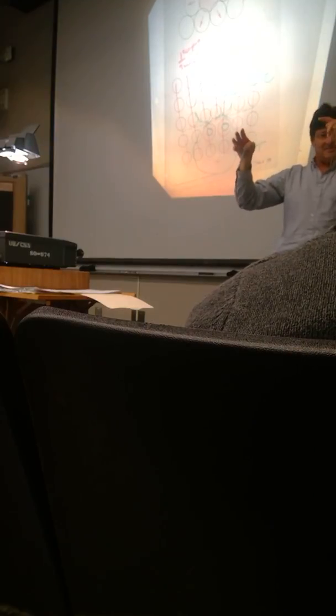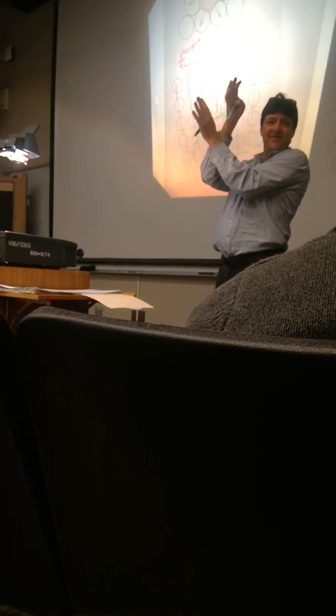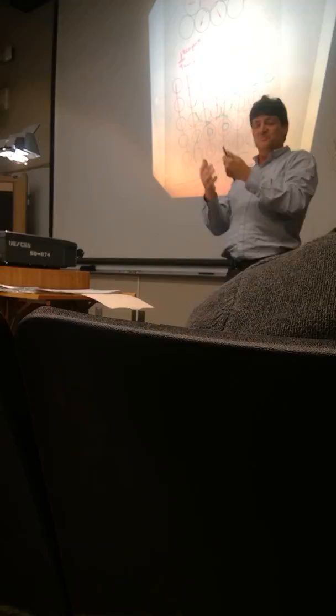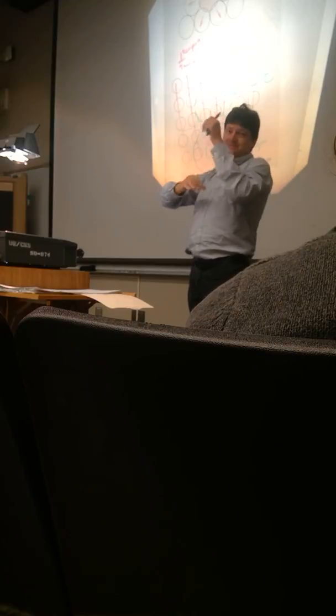You stop that, you let it sit long enough for atoms to diffuse. The impurity atom will try to get back to the dislocation, and now it actually got stronger by sitting there because the dislocations and atoms had a chance to recombine, and then you tested it again and it's gotten harder by just sitting there because some of the impurity atoms can get there.